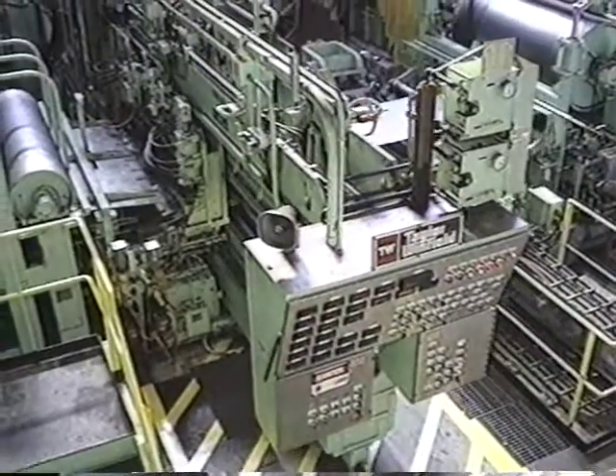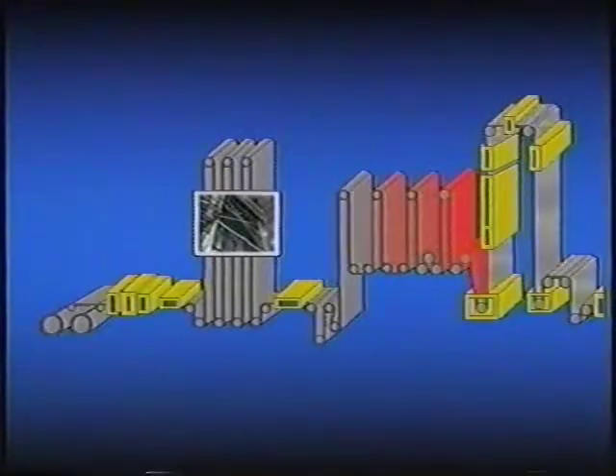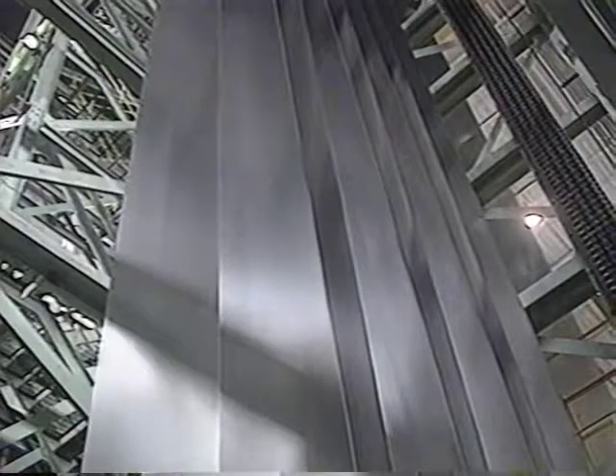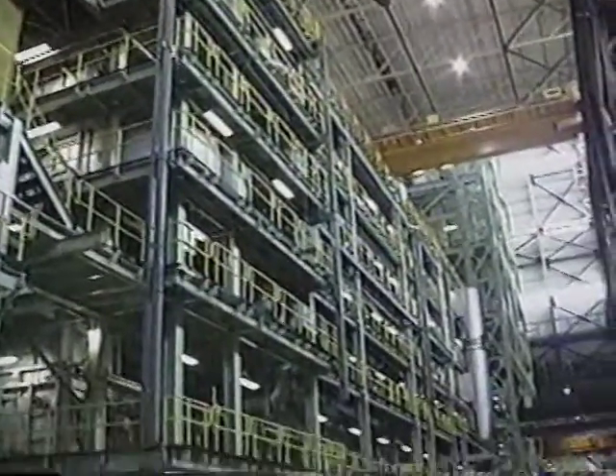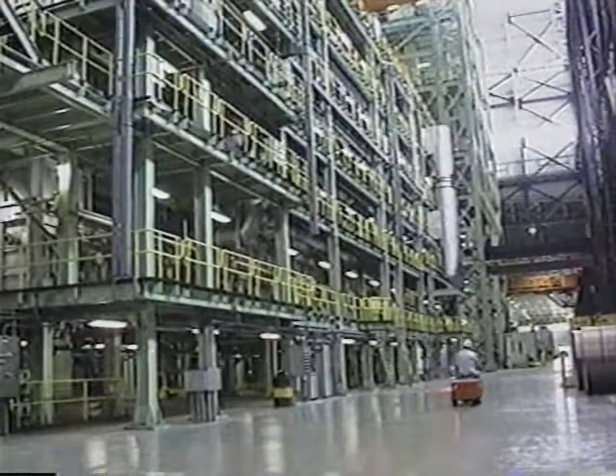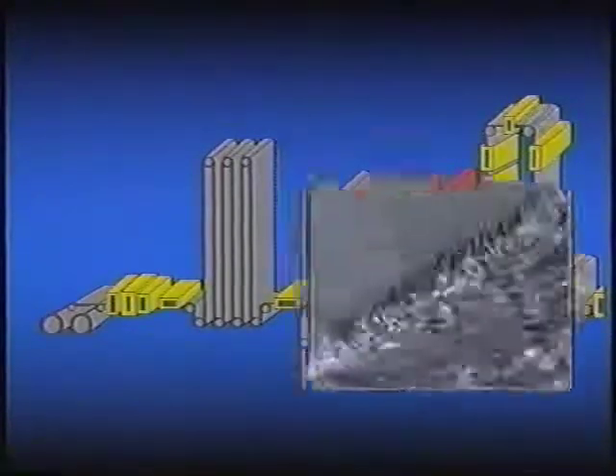A narrow seam welder joins coils from the entry reels, producing high-quality welds with minimal thickness. An entry looping tower permits continuous operation of the line with no slowdowns or interruptions for coil changes or welding. This means uniformly coated, consistent finished product for our customers. A three-stage cleaning system, including an electrolytic alkaline cleaner scrubber, ensures clean sheet for a smooth surface and excellent coating adhesion. Next, the steel loops through the all-radiant tube furnace, where it's heated to impart consistent final mechanical properties. The reducing atmosphere also improves coating adhesion. From the furnace, the sheet moves into the heart of the line, the zinc coating pot, where it gets the corrosion-resistant finish that adds good looks, long life, and value to our customers' products. As the sheet leaves the bath, our precision coating weight control system ensures a uniform coating.